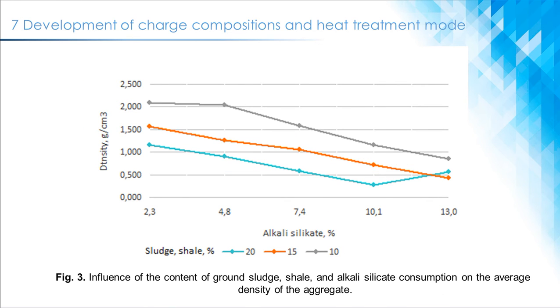Studies have been carried out to study the content of crushed sludge and shale for the aggregate average density. These studies' results are shown in Fig. 3 and show that aggregate granules' average density decreases almost linearly with increasing alkali silicate consumption. However, with a 15% content of crushed sludge, shale, and alkali silicate consumption of more than 10%, an increase in aggregate granules' average density is observed. A decrease in the melt's viscosity and the process of compaction, rather than porization, explain this. The combined effect of the milled components on the aggregate granules' average density is greater than that of each separately.